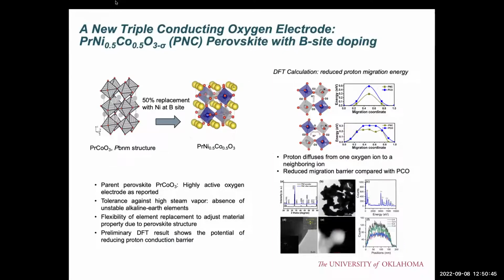So here I propose a parent material, a praseodymium cobaltite material, PrCoO3, and then I doped it with 50% nickel on the B site. The reason is because I want to dope 50% on the B site to trigger some changes. What kind of change? Firstly, I use DFT to calculate the proton migration energy within the lattice before and after this doping. After the doping, as you can see, we can significantly reduce the energy for the proton migration between different coordinates, through different octahedral sites.